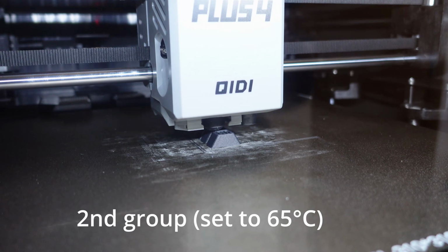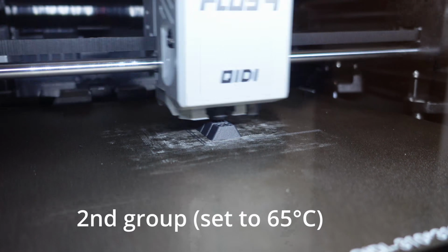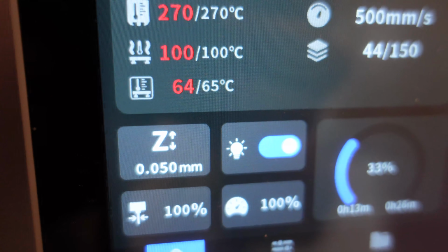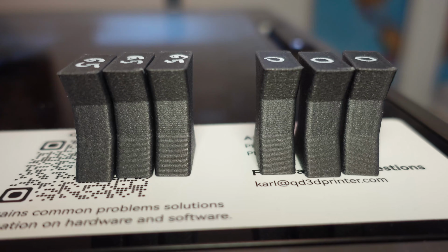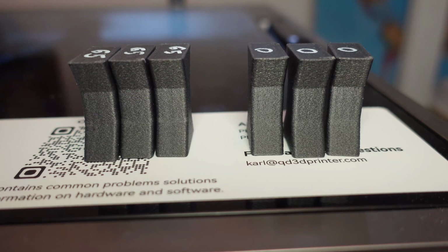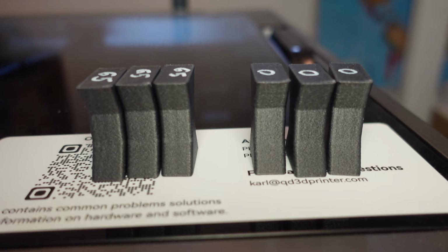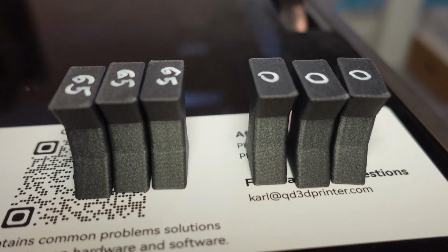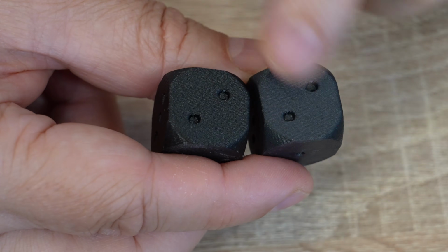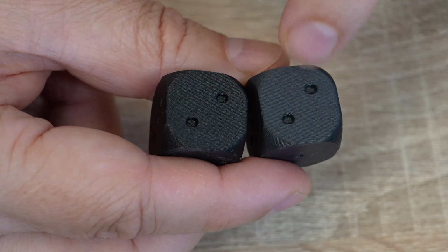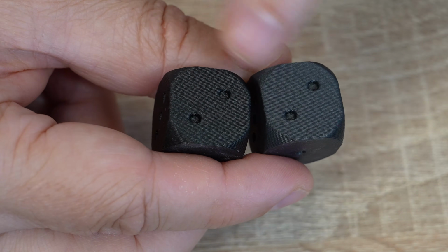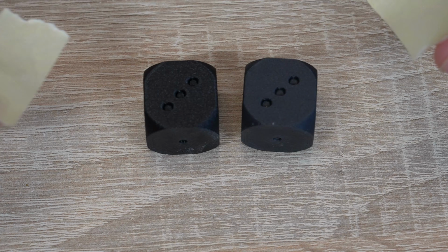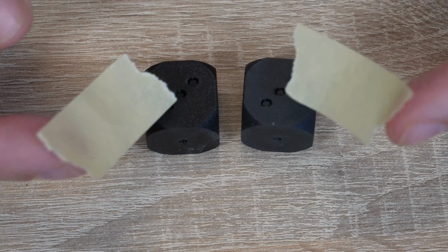It didn't even start with the smallest cross-section area, and the chamber temperature is already 64 degrees Celsius. The quality of those overhangs is great in both cases. I use 50% part cooling here, and we will see what's the difference in the layer adhesion. Even to the touch, the core is smoother compared to the regular carbon fiber version, but let's check the surfaces under the microscope. Yes, somebody suggested I do the sticky tape test.